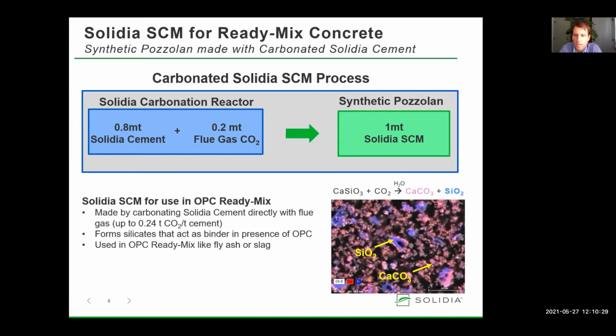The box at the top of the slide shows our process for making 1 ton of Solidia SCM. 0.8 tons of powdered Solidia cement is reacted with 0.2 tons of CO2, in this case from flue gas, to create 1 ton of carbonated supplemental cementitious material, or SCM, in powdered form. I'd like to emphasize that CO2, which in this case is an industrial waste product, makes up 1/5 of the final mass of the product. This means that only 0.8 tons of cement are needed to make 1 ton of final product.